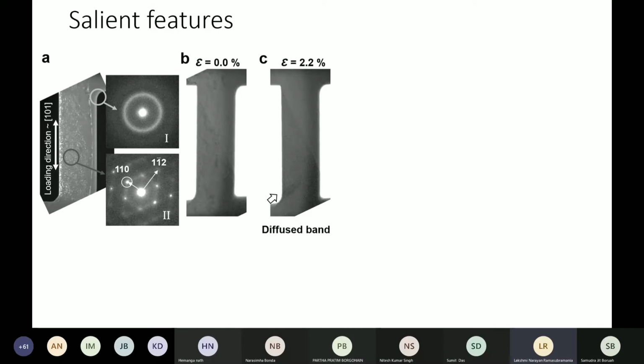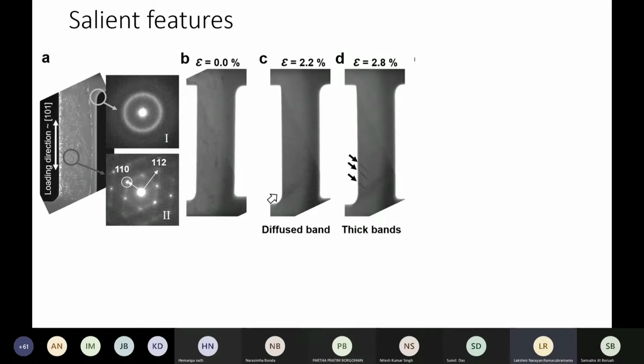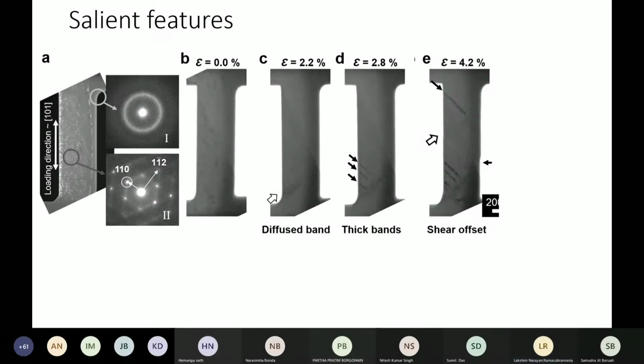If you look at the orientations given by these diffraction patterns, at 0% strain, nothing really happens. If the strain is 2.2%, a diffused band forms in the crystal at the bottom left corner. Here we have just rotated that image for ease of observation. And then you see that at 2.8% strain, perpendicular to these diffused bands, there are three thick bands forming, 3 or 4. In fact, you can see the fourth one is very mild, but these are essentially the thick bands that form. But these thick bands are not able to penetrate the amorphous layer.